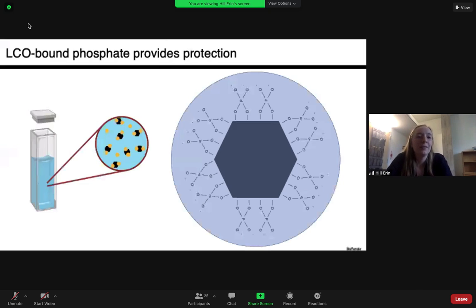With dissolution, we weren't totally sure what to expect. More stable and dispersed particles would mean that there's more surface area available for dissolution to occur, but with the phosphate binding to LCO, we may see a kind of protective coating around it that prevents dissolution. So we think that the combination of these things just resulted in a net neutral effect as far as dissolution goes.